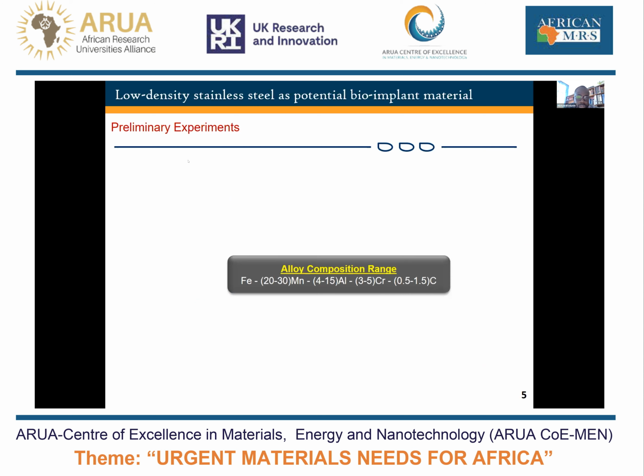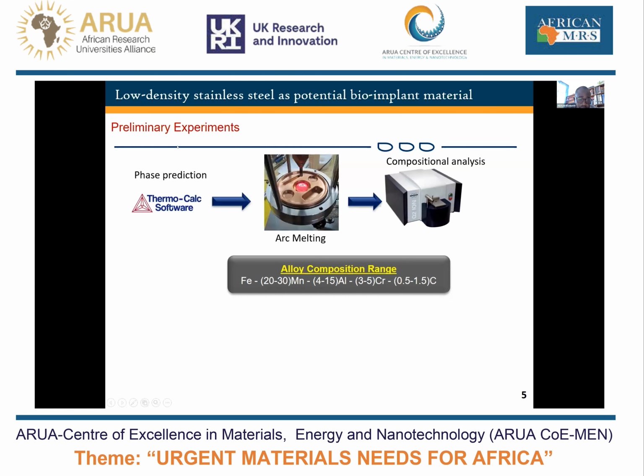So now let me give you an overview of the preliminary experiments we carried out. We looked at different alloys in this composition range, and we carried out Thermo-Calc analysis to do phase predictions, and then we did melting, and then we did spark analysis to come up with the composition, because when you're producing these alloys, aluminum easily evaporates, especially when you're producing via casting. So you need to really be sure of the composition that you're arriving at.